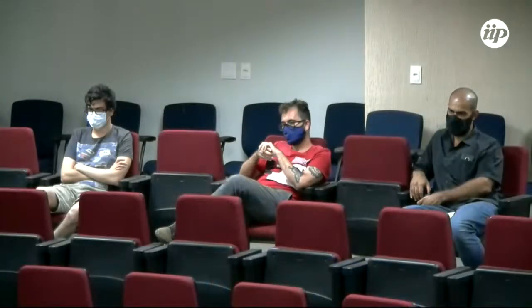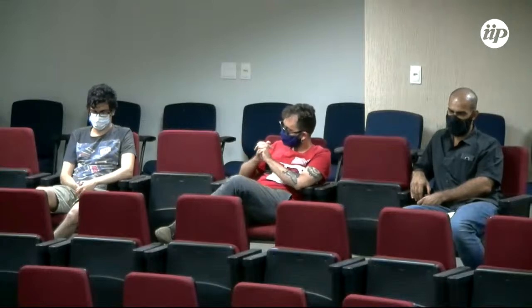Okay, because this time crystal notion of Wilczek, where you say that you can break spontaneously the translation symmetry, you can break spontaneously time symmetry. So there were lots of controversies about it. Then finally it was demonstrated that you could have time crystals involving condensed magnons. In fact, Wilczek wrote some papers, and some other group, about it involving yttrium iron garnet, the magnon condensation. It's almost like a Josephson oscillation. You have two yttrium iron garnets which are weakly coupled. Then the magnon condensate goes back and forth, and it lives for a long time, the coherent oscillation. So which was connected with time crystals. So I was wondering whether you will comment on that.